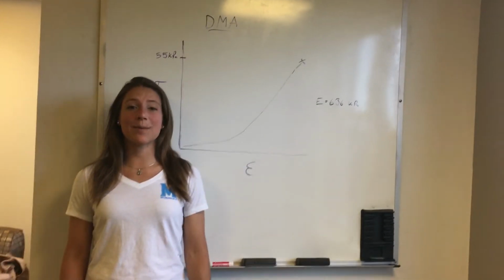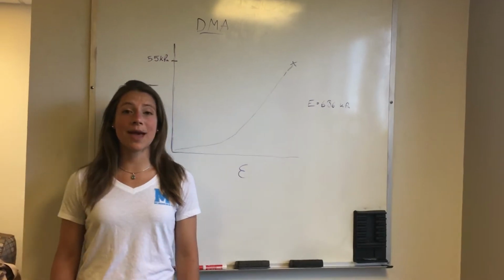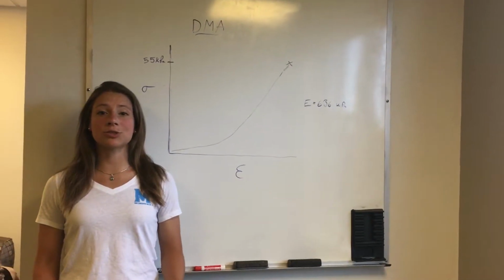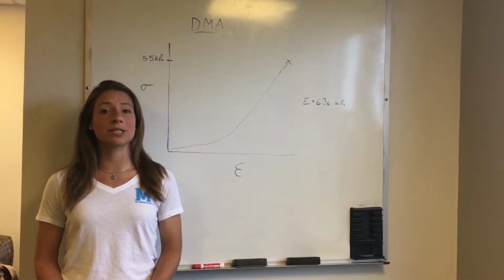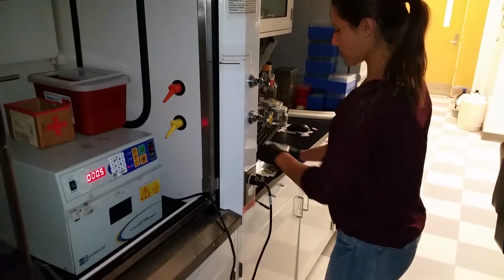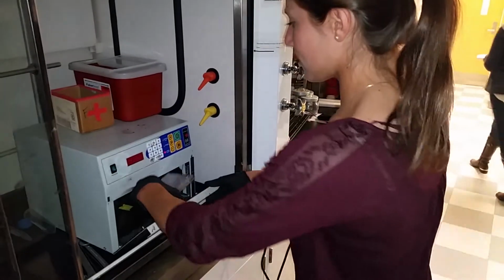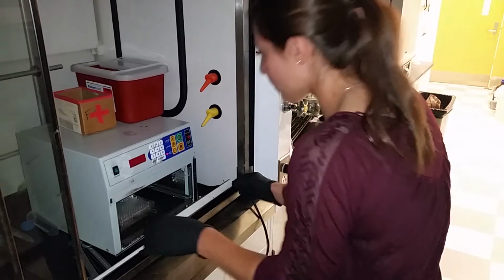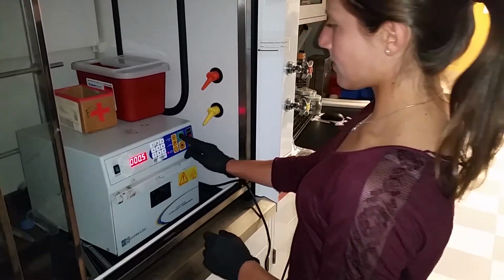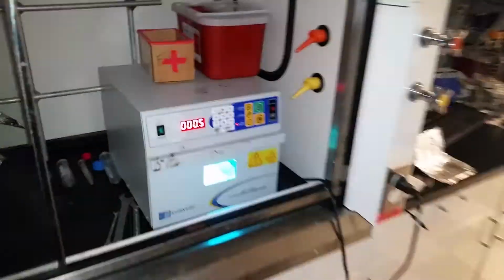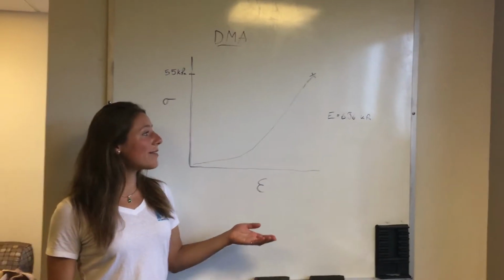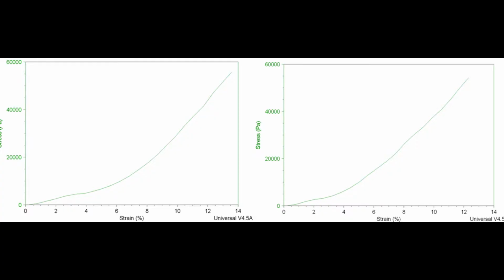I'm going to explain dynamic mechanical analysis, or DMA, which was used to get stress-strain curves and therefore the compressive modulus of our hydrogel samples. First, we cross-linked the samples in 96 well plates in the UV box for varying amounts of time. We then removed the samples from the 96 well plate and cut off the menisci before loading them into the machine. We found that our samples had an average compressive modulus of 636 kilopascals and an average failure stress of 55 kilopascals.